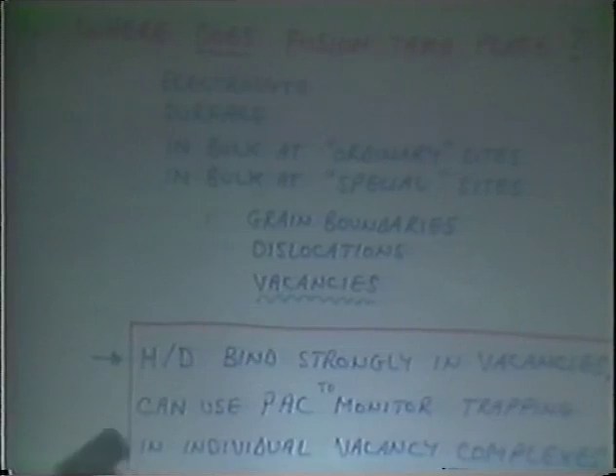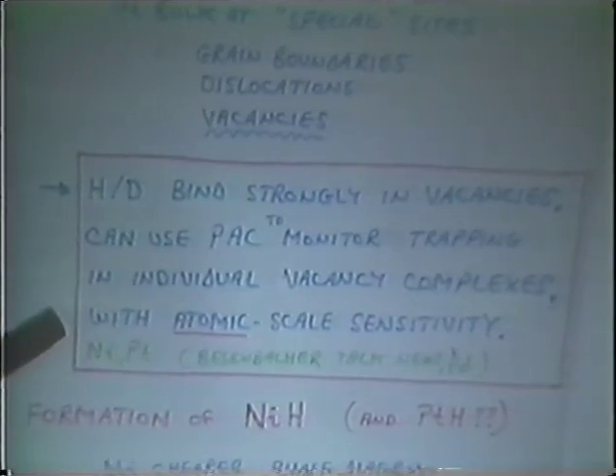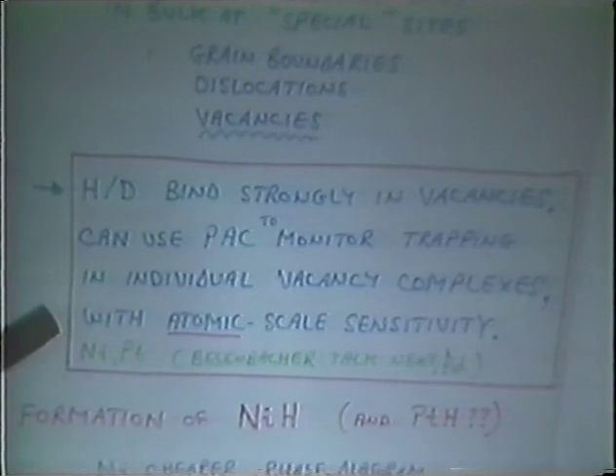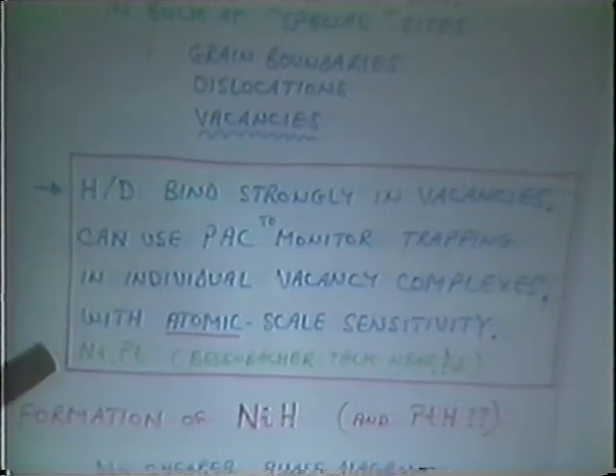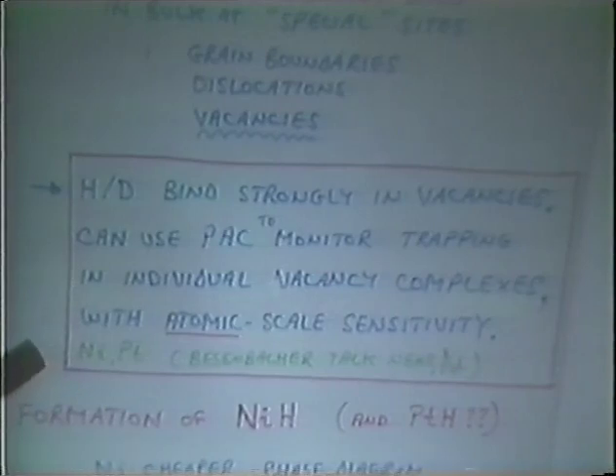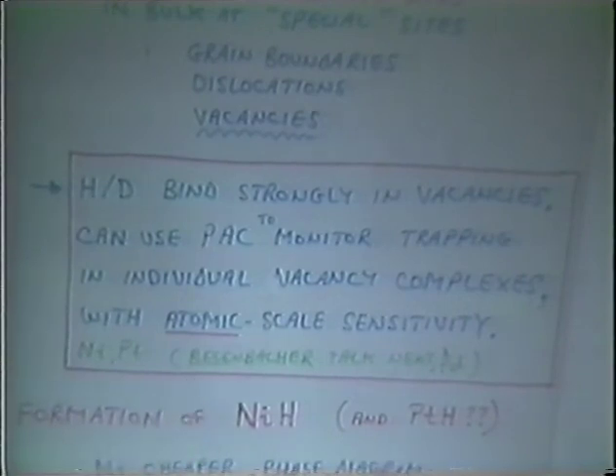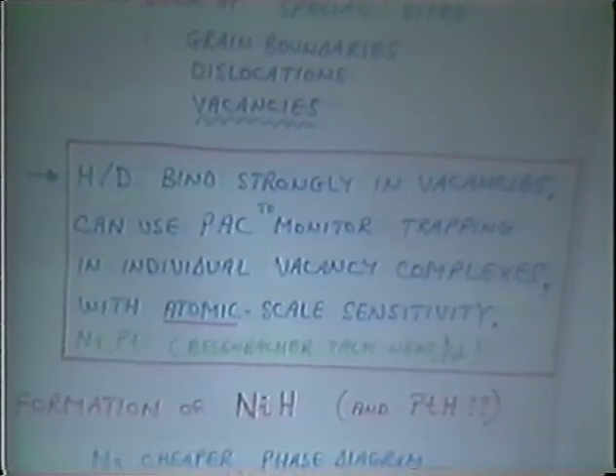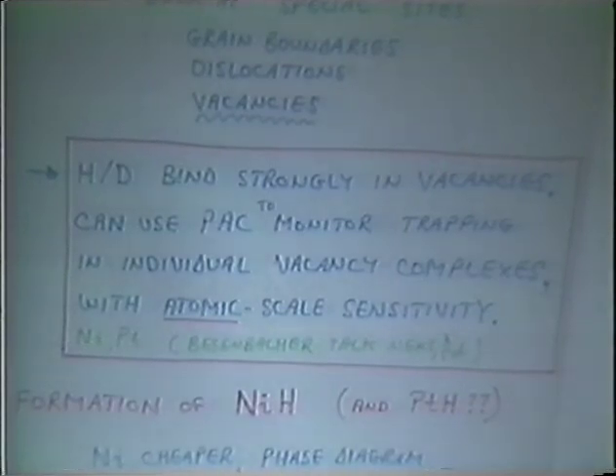Now, it's a fact that hydrogen and deuterium bind quite strongly in lattice vacancies, atomic vacancies, and the perturbed angular correlation technique is useful because we can monitor trapping of individual hydrogen atoms in lattice vacancies next to impurity probe atoms with atomic scale sensitivity. We can also observe multiple trapping of hydrogen atoms in vacancies. The work I'll tell you about focuses on nickel and platinum because we haven't done any work, it's just starting now, on palladium. In the next talk by Biesenbacher, you'll hear a discussion by a different technique of hydrogen trapping in vacancies in palladium.